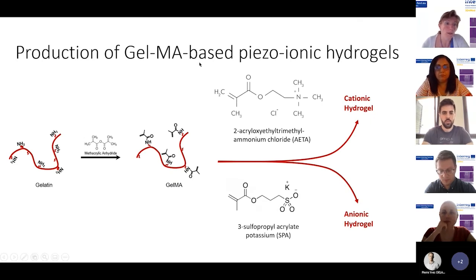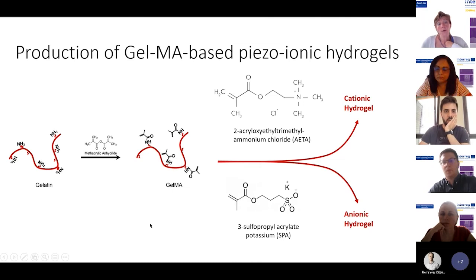So we start based on a gelatin polymer. Gelatin is a polymer which is found in the human body, so it's a natural polymer that is perfectly biocompatible and biodegradable. But in order to make it a more variable hydrogel, so that more compounds can be added to the hydrogel, we put it together with methacrylic anhydride in order to produce the GelMA polymer. This way we have more functional groups available in order to add other components, such as a cation or an anion, in order to make these piezo-ionic hydrogels. So we can then develop a cationic hydrogel or an anionic hydrogel, as has also been explained in the presentation of Nicolas.